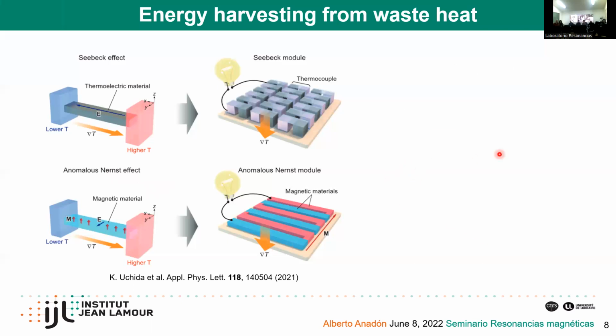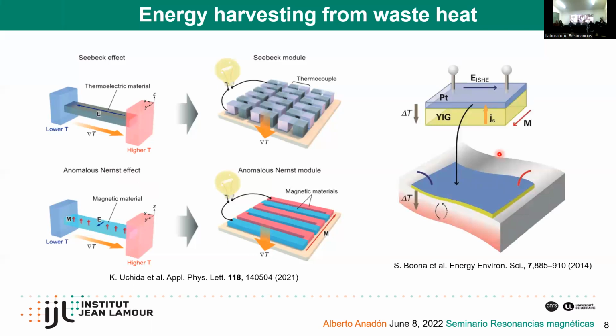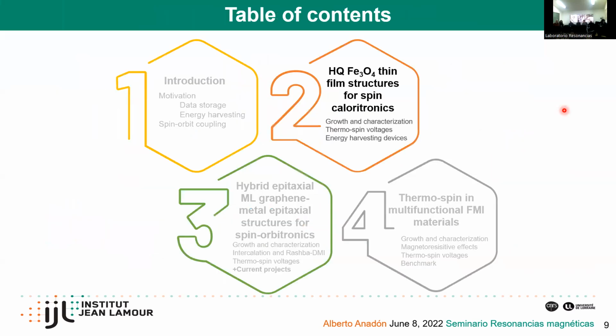But we can do this by taking advantage of a spin-orbit interaction. If we make devices like this with a bilayer, with a ferromagnet and a material with high spin-orbit coupling like platinum, we could take advantage of this spin-Seebeck effect to obtain energy. So I will move then to the first part of my talk. And now I will discuss magnetite thin film structures for spin caloritronics.